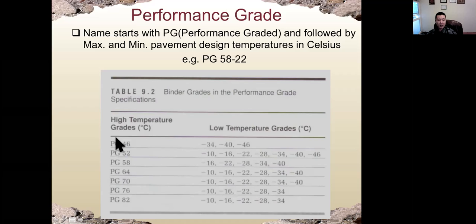So for a certain grade, we have high temperature. For example, we have 46 degree, 64 degree, or 82 degree. So it depends on where you want to put your asphalt. Okay. So in warm temperature, tropic weather, we're going to increase the design temperature. In Alaska, you're going to reduce your low temperature grade. For every grade of high temperature, we have several different low temperature grades. For example, for PG70, we have -10, -16 to -40 to choose from. Okay. So then let's look at how we can select the performance grade of the asphalt depending on the local climate.